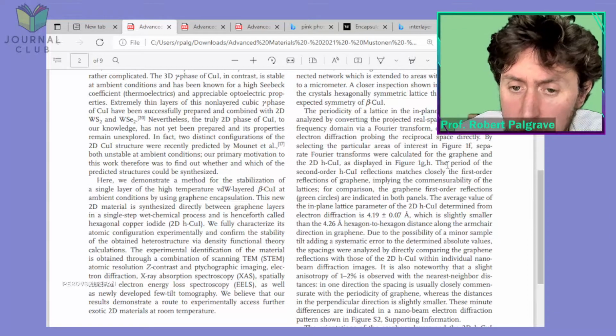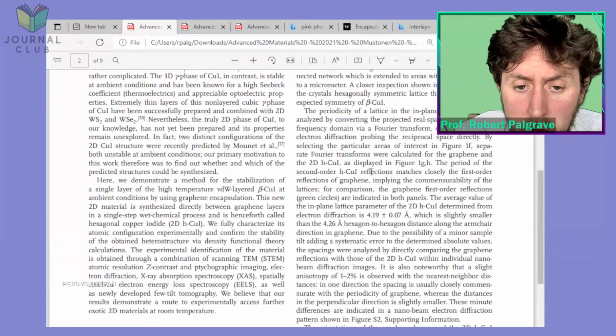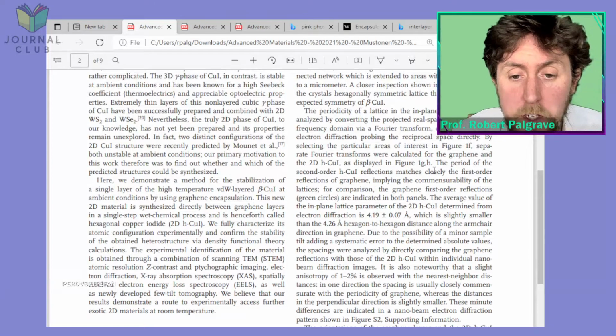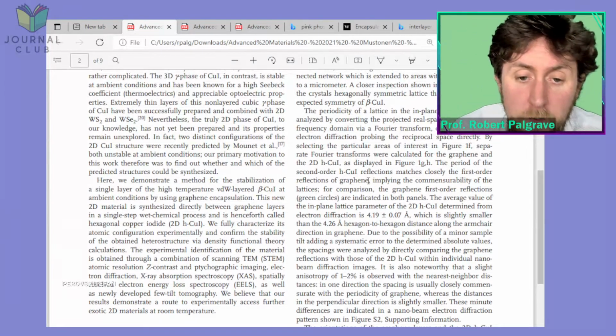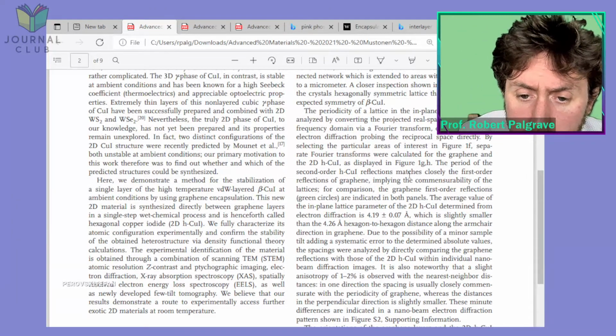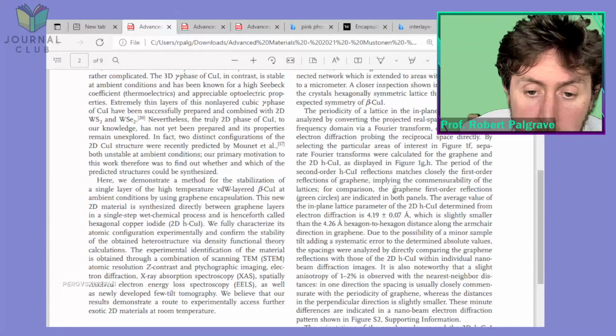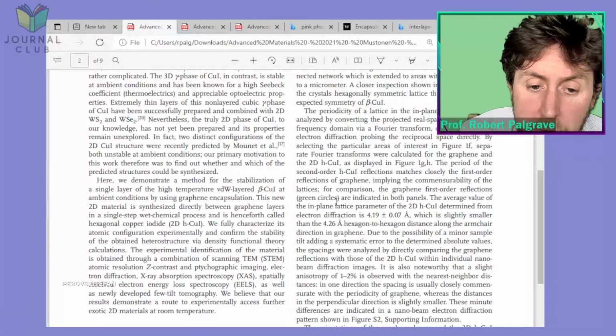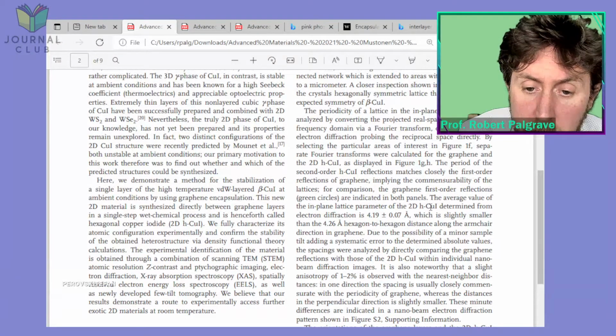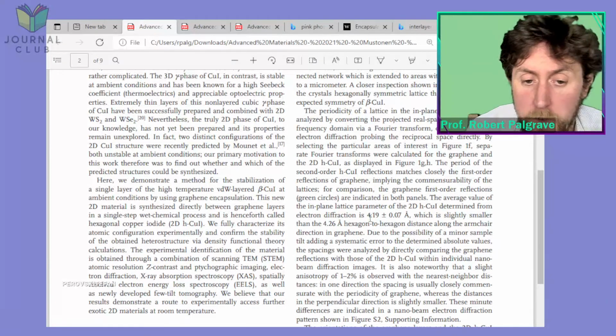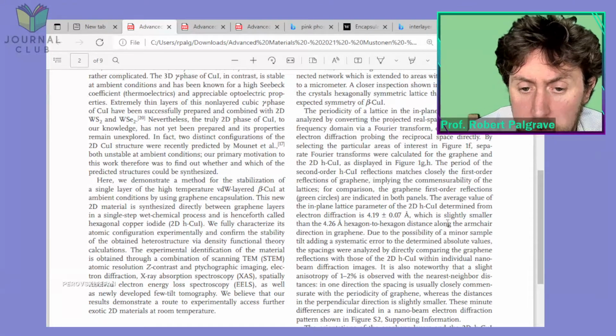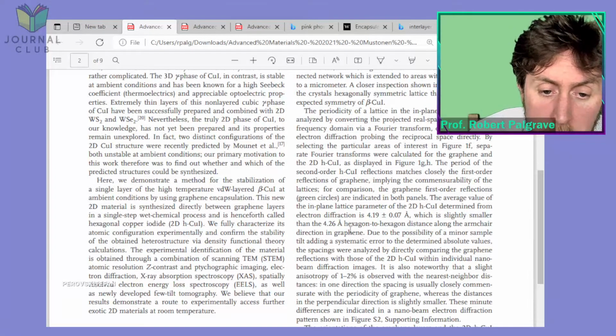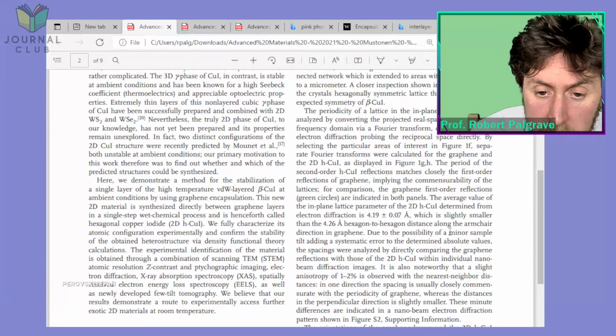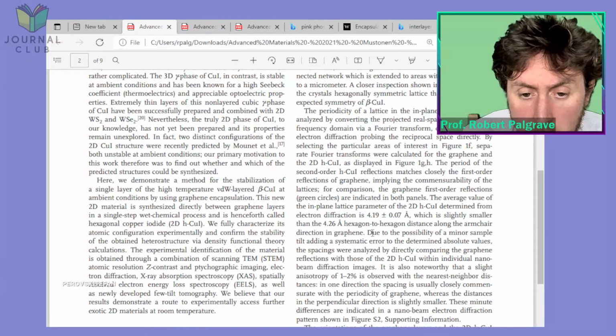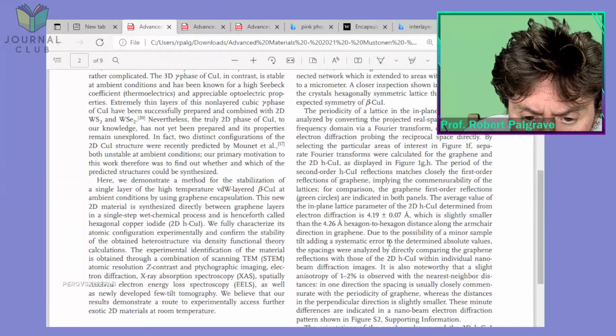Okay, interesting. The period of second order hexagonal cuprous iodide reflections matches closely with the first order reflections of graphene, implying commensurability of the lattices. For comparison, graphene first order reflection, green circles are indicated in both panels. The average value of the in-plane lattice parameter of the 2D hexagonal cuprous iodide determined from electron diffraction is 4.19 angstroms, which is slightly smaller than the 4.26 angstrom hexagon to hexagon distance along the armchair direction of the graphene. Okay.